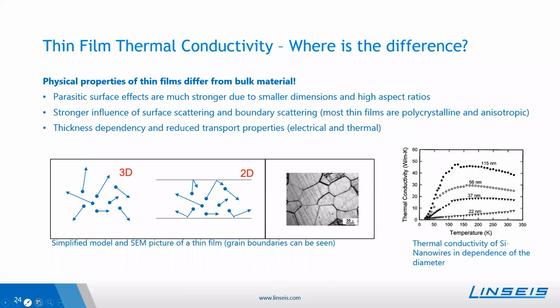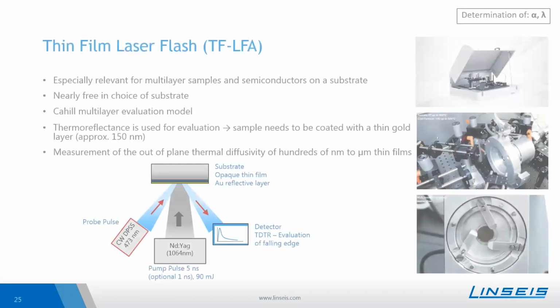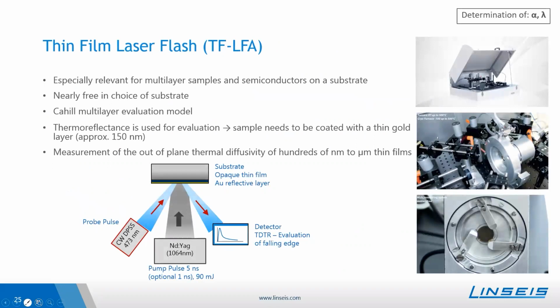as it is plotted here, that the thermal conductivity significantly reduces by reducing the thickness of a material. For these tasks, especially when going down to low micrometer and nanometer ranged thicknesses, we have to further special setups. So on the one hand, the thin film laser flash, it is especially relevant for multi-layer samples and for semiconductors on substrate. It also allows the determination of thermal diffusivity and thermal conductivity.